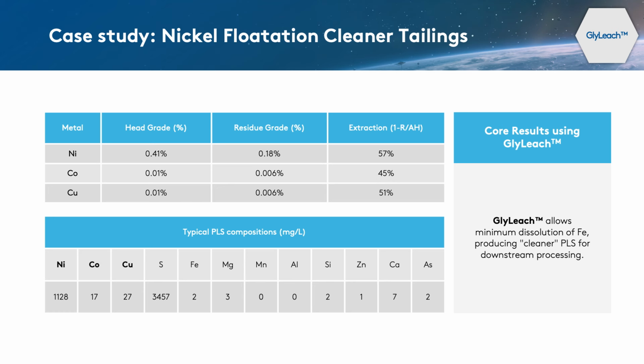Next case study is related to a tailings sample. So this particular material has only 0.4% of nickel, 0.01% cobalt and copper. With Glyleach, which is using sodium hydroxide to adjust the pH and maintain it, 57% of nickel was extracted, further reducing the nickel residue grade to 0.18%. At the same time, we also achieved 45% of cobalt extraction and 51% copper extraction.